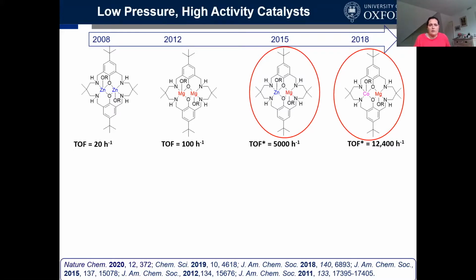My group have worked in this area for a number of years, and we've been particularly interested in bimetallics, as I said. We started out looking at two zincs in a particular macrocyclic ligand framework, which you can see here. They had quite low activity, turning over about 20 turnovers an hour. But they were unusual because they worked at 1 bar pressure of CO2, so they could really turn over under very accessible conditions, low CO2 overpressure.